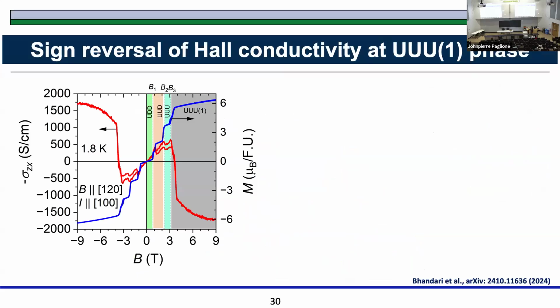Okay, so what is interesting is that now there are these different steps in the magnetization. We measure the Hall conductivity, and in the Hall conductivity you see these little steps going up here. And then when it enters this region, boom, it comes way down. And this is where people have fallen down. There is one even published in PNAS saying that this is a large topological Hall effect, because this was not supposed to come and this is a huge jump. This is not a topological Hall effect. This is a change in electronic structure because the spin structure becomes different.